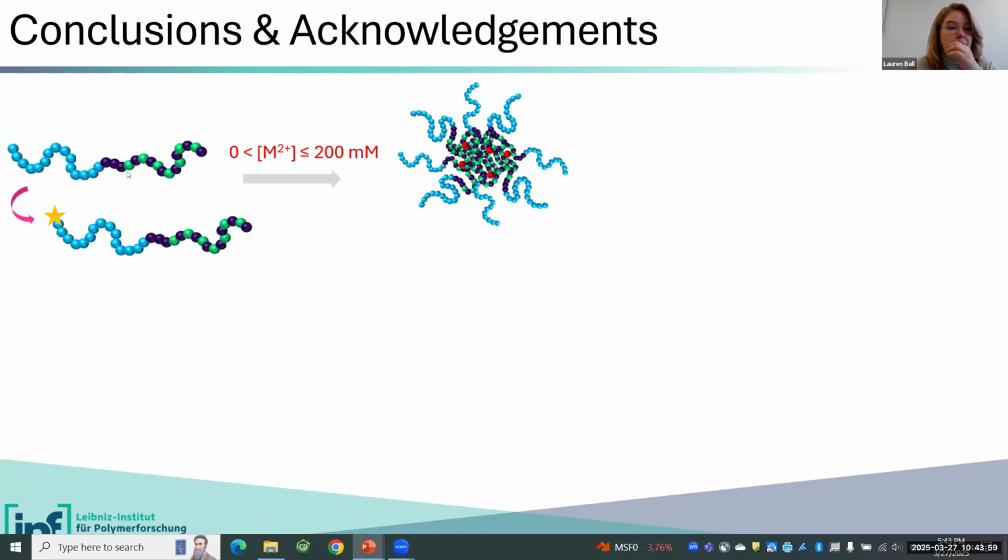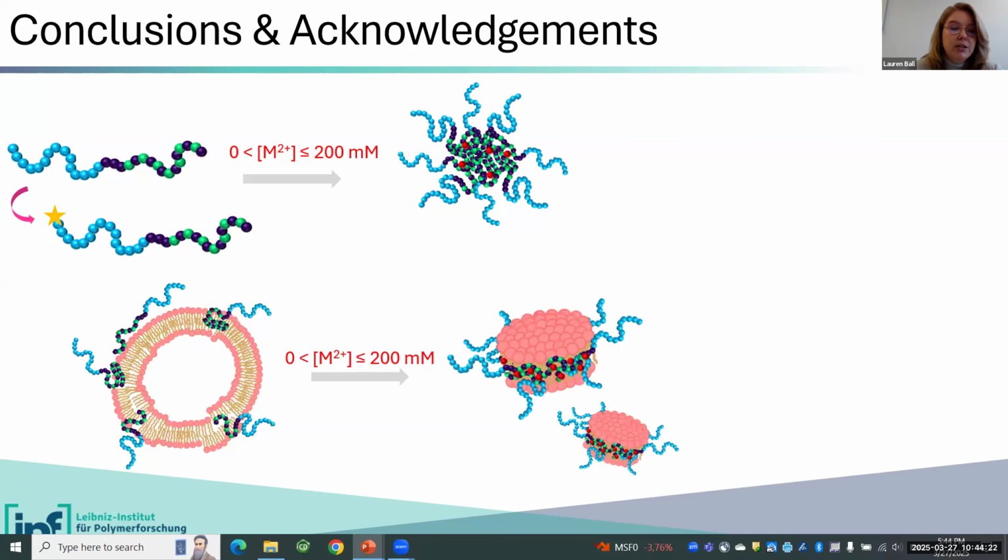Another nice thing about these block copolymers is essentially you retain your RAFT end group at this chain end, and that can be aminolyzed to make a thiol, or you can do a Michael-type reaction and insert a biotin moiety, which we've already successfully done in our lab. So these block copolymers can also then be nicely employed in surface immobilization procedures.